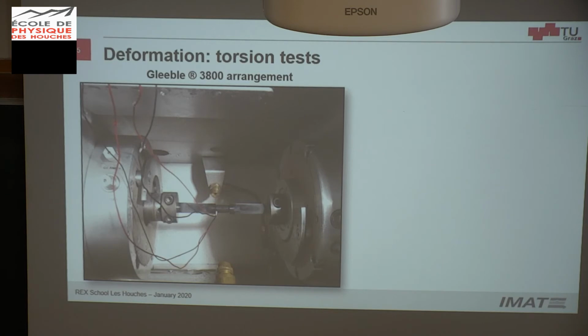So I'm going to show only one of my favorite experiments, which is the torsion test, and we are doing it in a Gleeble machine. I don't know how many of you know the Gleeble machine. Yeah, 1, 2, 3, 4. Ah, a lot. Great. So you know all the pros and cons, or most of them. It's fast. You can control the temperature very well because the thermocouples are attached to the sample. You can do in-situ water quenching, which is essential here if you want to study dynamic recovery. Otherwise, you will have static recrystallization during cooling, which occurs very fast.